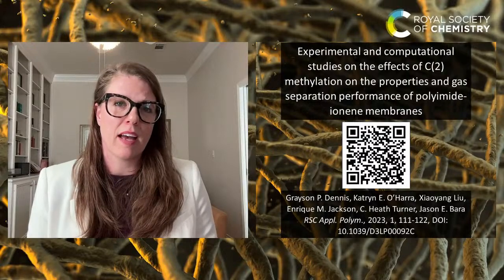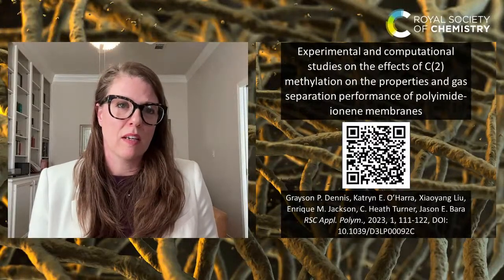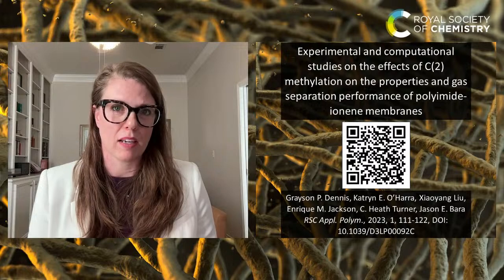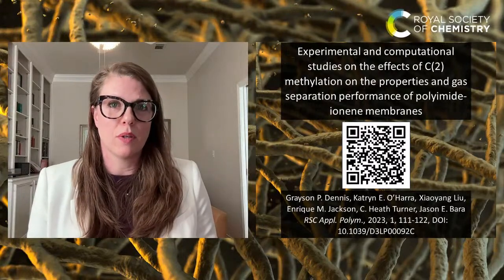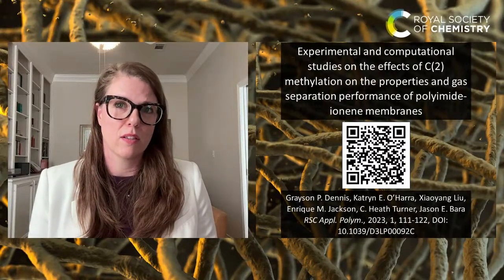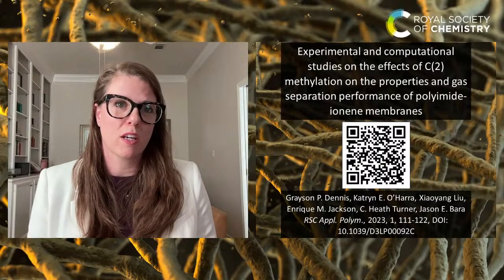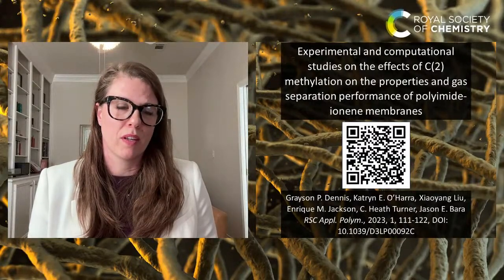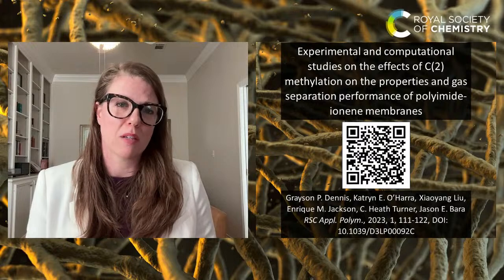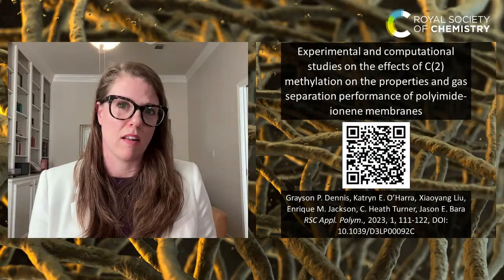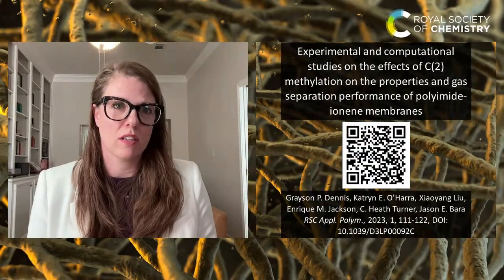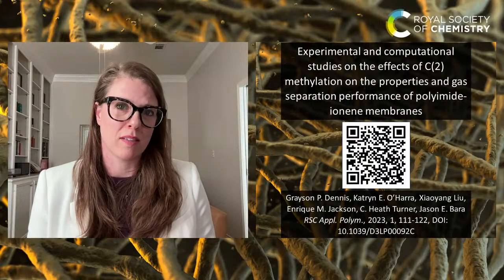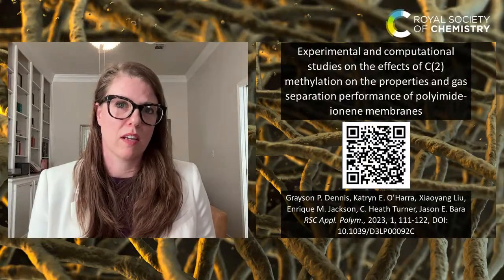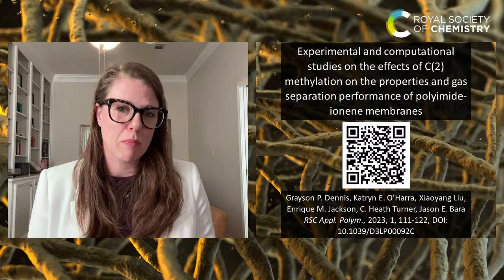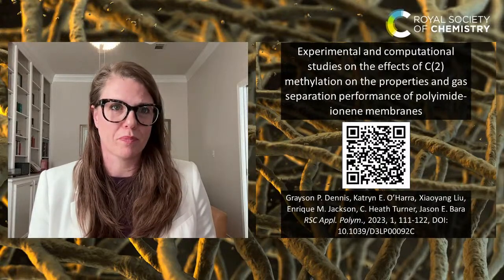permeation. As expected based on computation, methylation decreased the chain packing, but this also led to diffusivity significantly decreasing, with a slight increase in solubility of CO2. So the methylated polymer had a lower gas permeability than the non-methylated analog, guiding researchers to tailor interchain interactions to impact performance using a combined computation and experimental approach. This paper is available in the first issue.